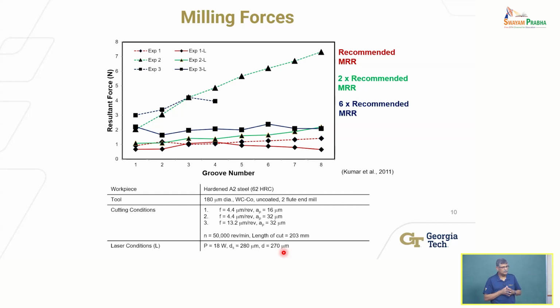But we used a nominally 1 micron wavelength beam. Beam size coming out of the collimator is 5 millimeters, and then you use optics to bring it down to 280 microns, right? You can do that. You can play with all of that. So anyway, the point here is to show the benefit of this thermal softening idea, right? So here it's showing you that we milled 8 grooves.